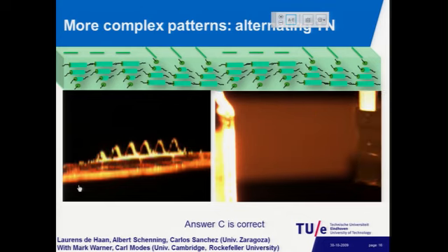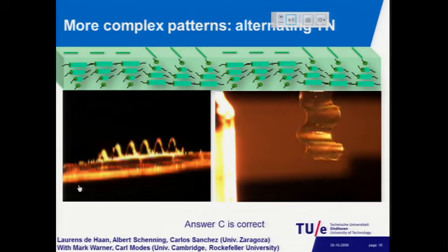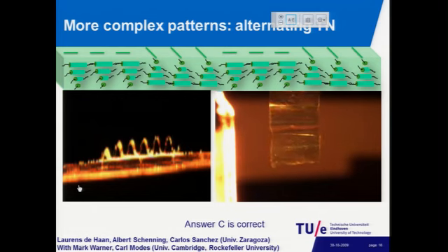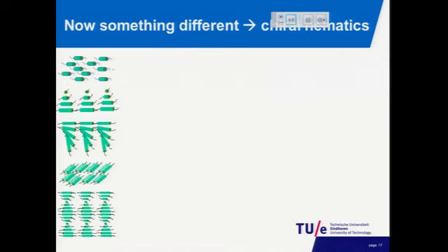So here we bring it again to this lamp, and you see that it goes from straight into this harmonica shape. If you do it sideways, then you don't see so much effect because the absorption is less. If you rotate it further, you will see the same. So now we have created geometrical changes. We created morphing, so to say.